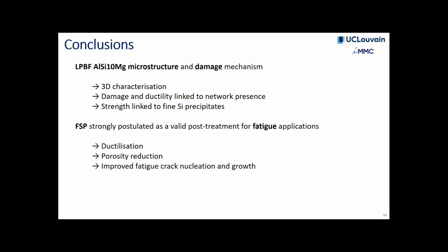It's a very interesting question, Roland. Camille is currently investigating that, actually. We continue having a more industrial project on this. This was more the scientific part of it. And in this industrially based project, we're really thinking about that. I would tend to agree with you that you could probably treat the surface, because we know that it's subsurface porosities that are usually initiating fatigue cracks. So we believe that indeed, if you're just looking at the surface, that will be more than enough. Maybe it would even be enough not to have a pin, just the shoulder part could possibly be sufficient. So still something we're investigating. Okay, thank you.